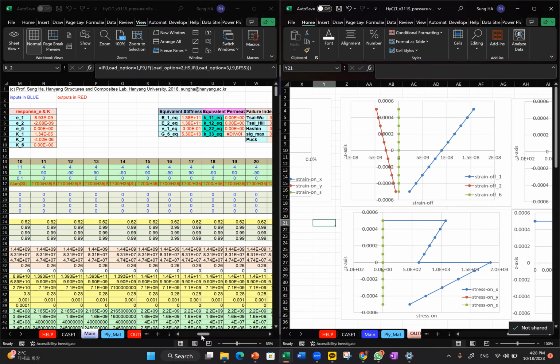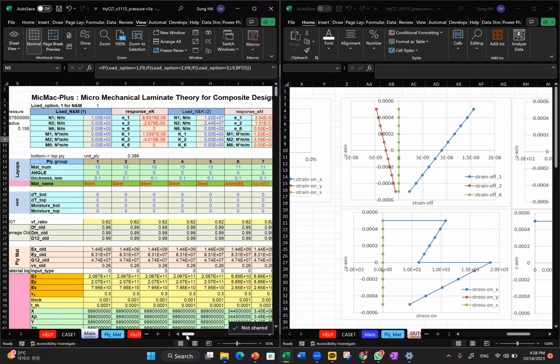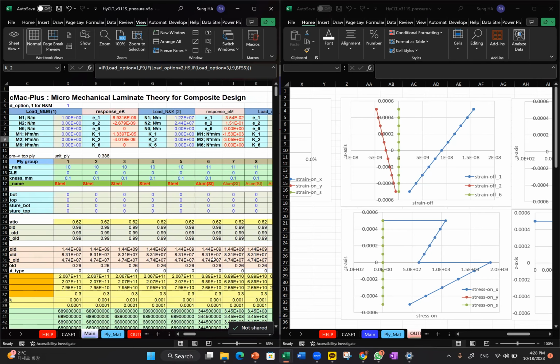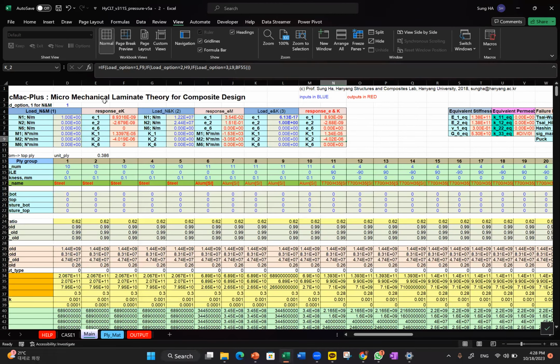Okay, so this is the unsymmetric case caused by layering different isotropic materials. This is very important in laminate composites. Again, even for different isotropic materials, steel and aluminum, this will cause curvature